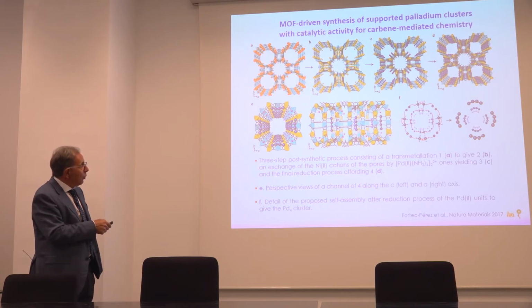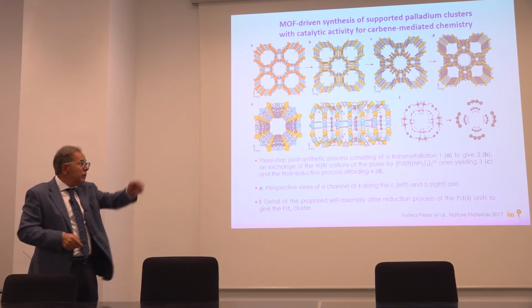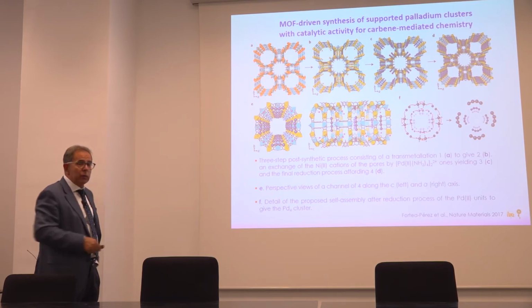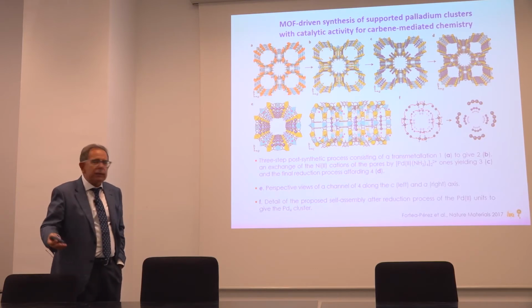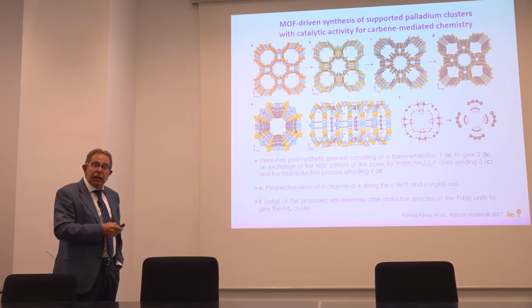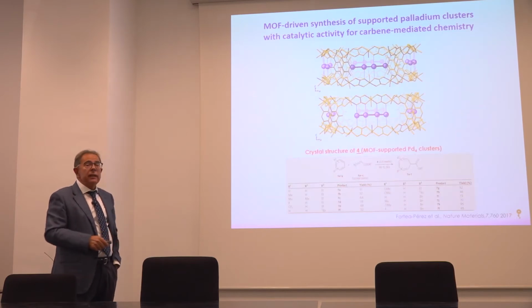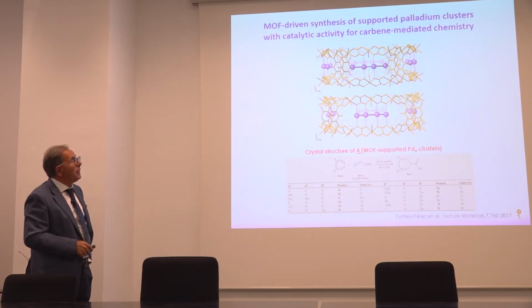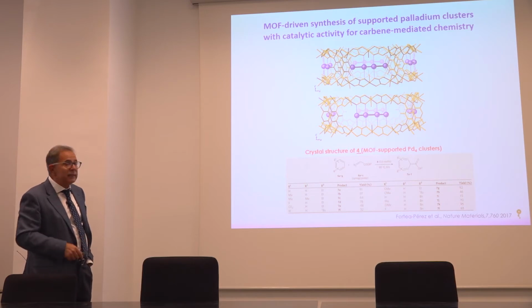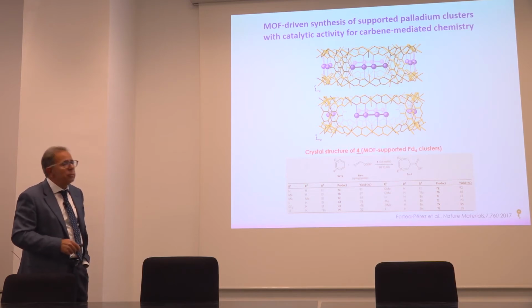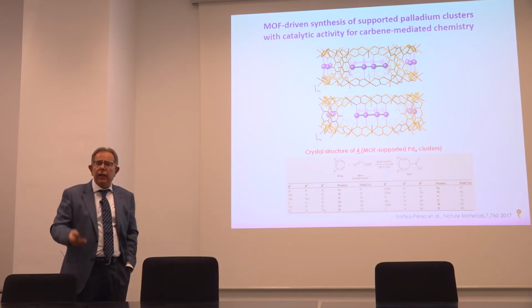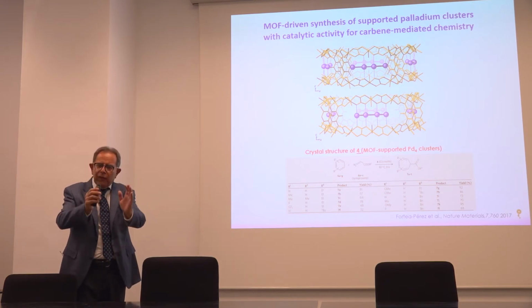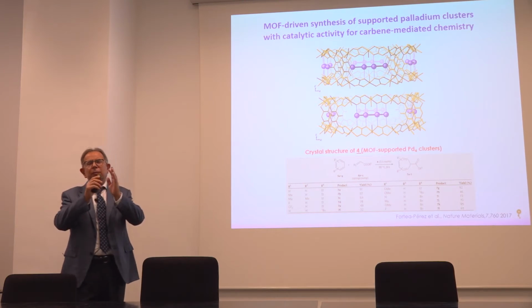Those clusters are at the wall, as you see. This will be the view along the channel, okay? And that will be another view. Very well-defined, and reasonably stable at the temperatures at which the MOF was stable. And it was active. We tried this for a carbene-mediated reaction with the diazoacetate here, and the results we obtained on yields and selectivity were at least at the state of the art for this type of reaction. So we could make well-defined four-atom clusters of palladium.